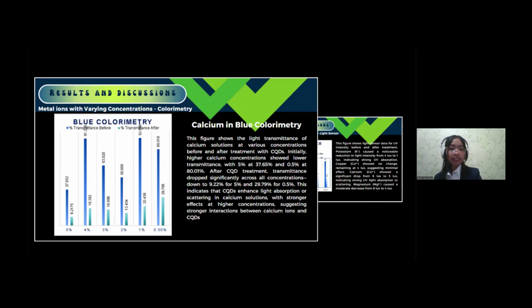After adding CQDs, light passing through dropped a lot at all levels. For example, for the 5% calcium solution, transmittance went down to 9.22%. This means the stronger the calcium concentration, the stronger the interaction between CQDs and calcium.